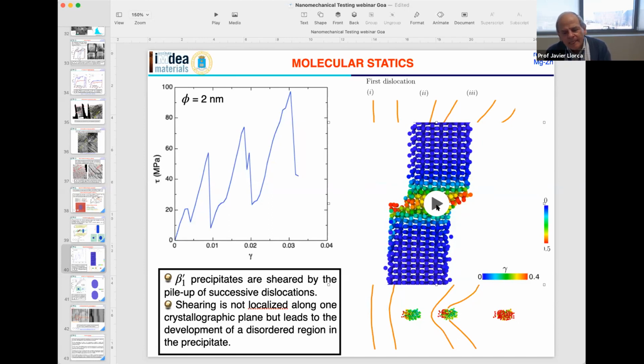Okay, yeah, this is really fascinating. Thank you. And that happens particularly in magnesium because dislocations in magnesium pile up in the basal plane, because the critical resolved shear stress for slip of dislocations in the basal plane is so low that it's very easy to create a pile-up of dislocations. That's the reason why eventually you have so many basal dislocations that they just destroy the precipitates.